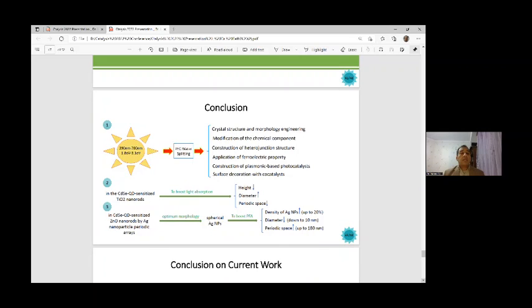Here a comparison between two quantum dot sensitizations, of TiO2 and ZnO nanorods, is presented. You can see, in the cadmium selenide quantum dot sensitized TiO2 nanorods, as a conclusion, to boost light absorption we should lower the height and have higher diameter and periodic space. We should have a periodic array structure.